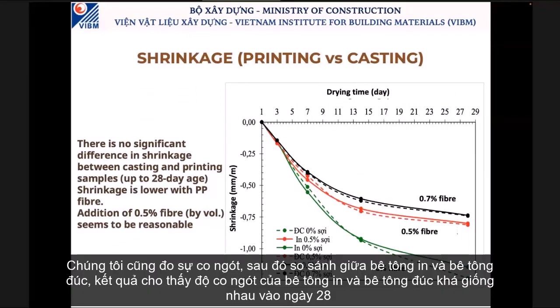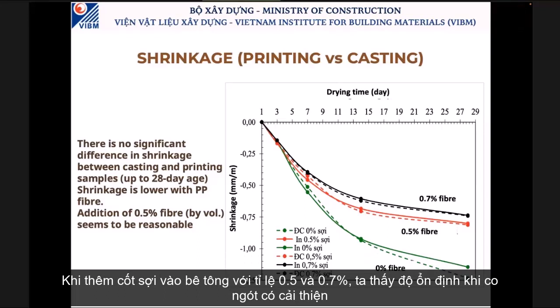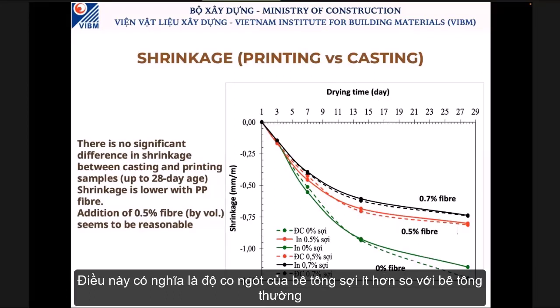And we also measure drying shrinkage and compare the printed specimen and cast specimen, and we found that it is actually quite a similar result up to 28 days. And when we add fiber 0.5% and 0.7%, the drying shrinkage improves. That means the value is lower than the non-fiber specimen.